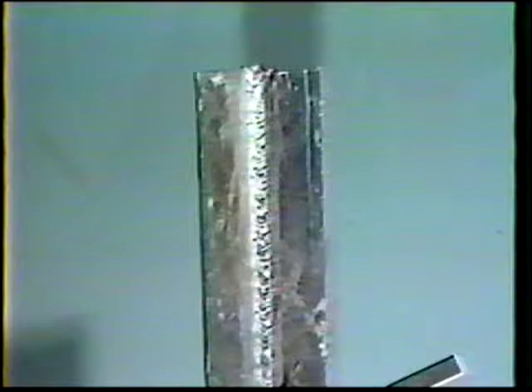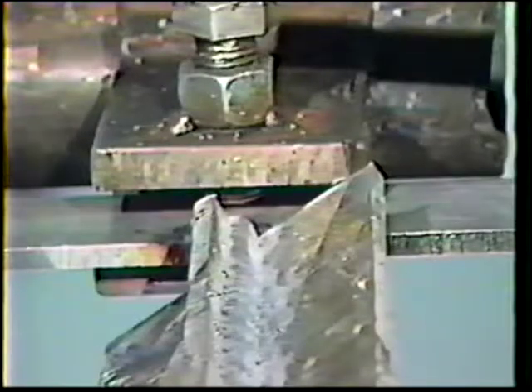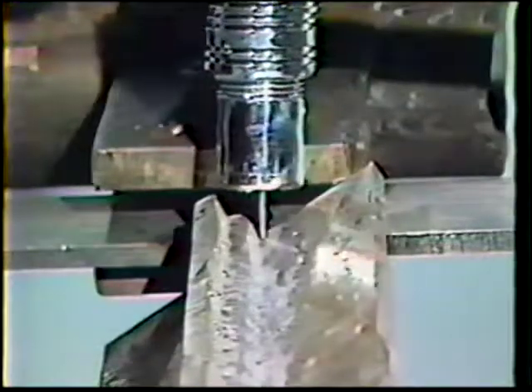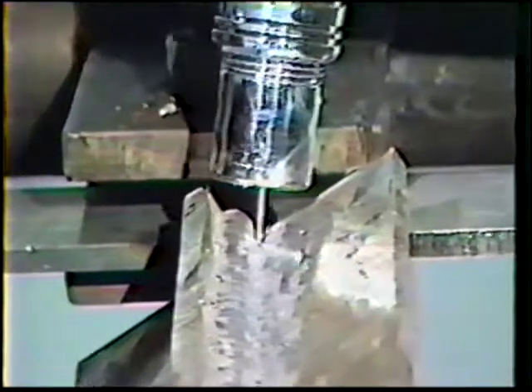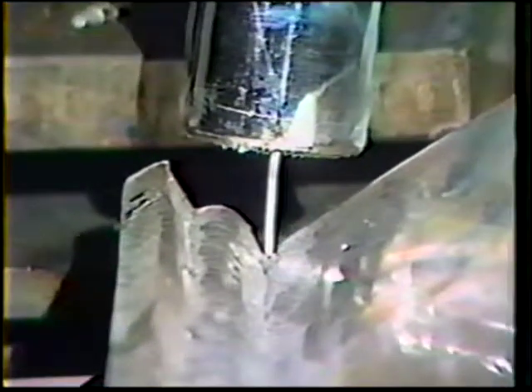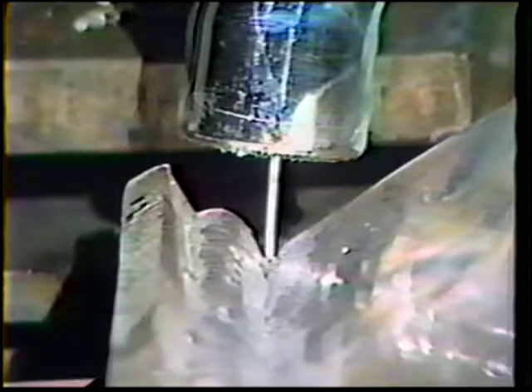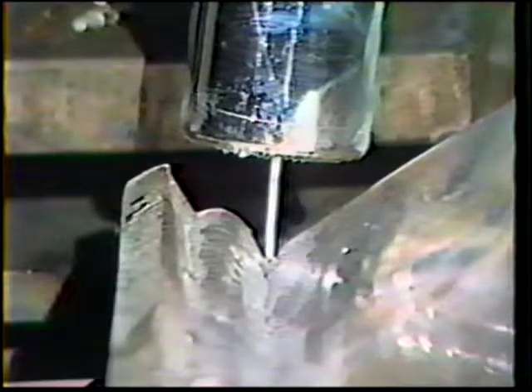The finished face should be 3/8 inch wide and flat to slightly convex with no undercut. Deposit all second beads before making the third pass. The third and final pass will use a 30 to 40 degree work angle and the same travel angle as before to overlap the previous bead by 1/2 and completely fill the joint. Move smoothly up the joint with the same slight weaving motion used for welding the second bead.